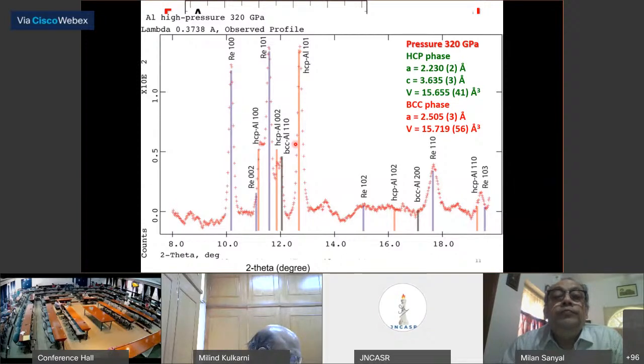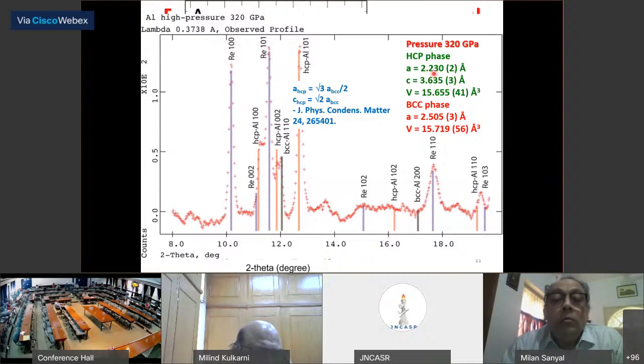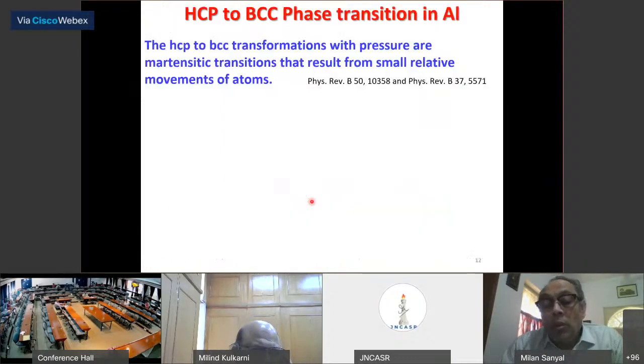such a high pressure. And this is at 320 gigapascals, and you can see the HCP phase, you can actually find out. And this follows the rule, which is the HCP to BCC ratio. You can exactly see, and we have got the BCC phase.